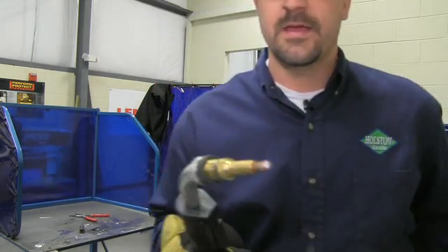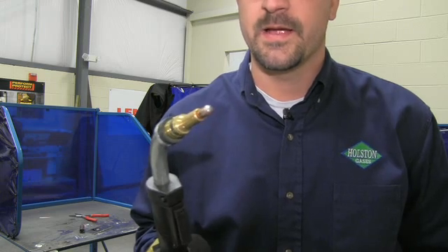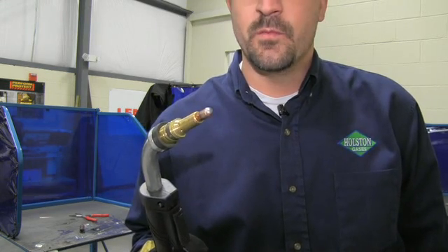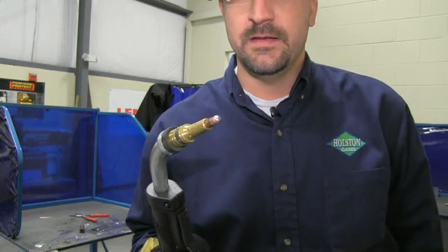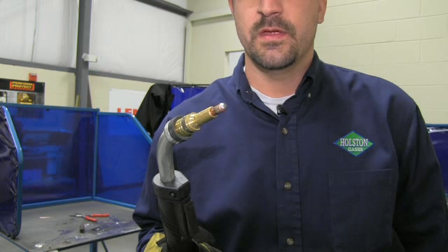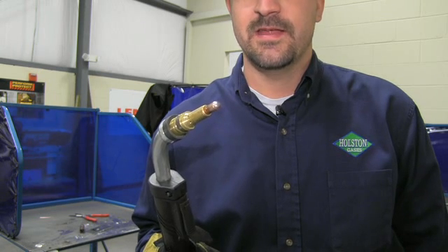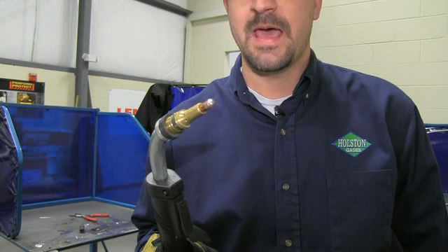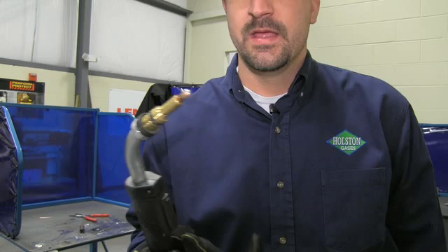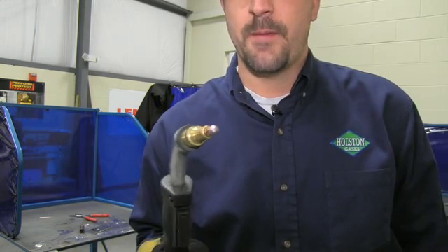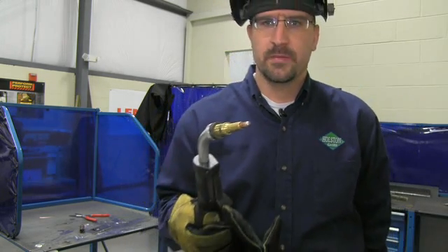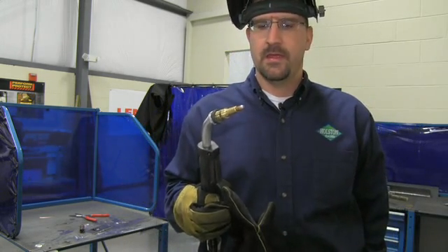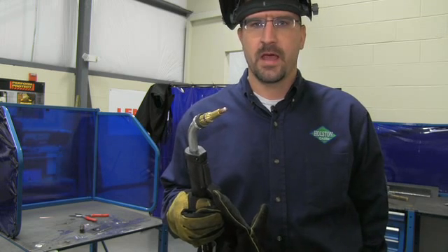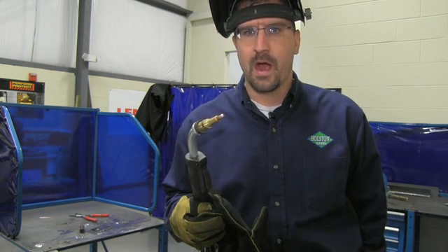So as you can see right here, this is an excellent example of burn back. Burn back is caused when the wire does not feed, and the voltage burns the wire that's already extended out of the tip, burns it back to the contact tip. And so this is a very frustrating problem. It's a very common problem, especially with robotic welding. And burnback is mostly caused by some type of inconsistent wire feeding.